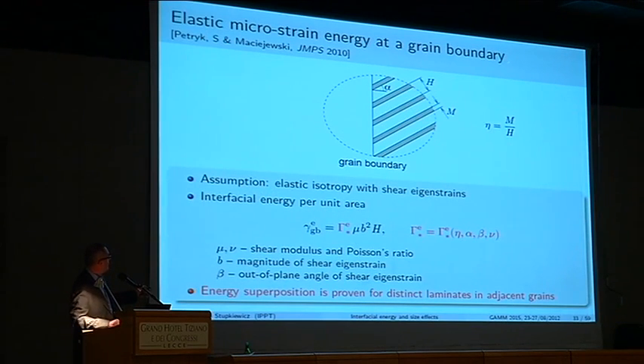Now we go to the grain boundary. As I told you, grain boundary can also be seen as a kind of microstructure interface. So imagine a grain boundary between two grains, and in one grain you have martensitic plates which terminate at the interface. So again, there will be this kind of local strains that would accommodate incompatibility at the interface. And we would like to know this energy as well. So here the situation is a little bit more complex, because you can imagine that the grains are arbitrarily oriented with respect to the interface, so a lot of unknowns, and also